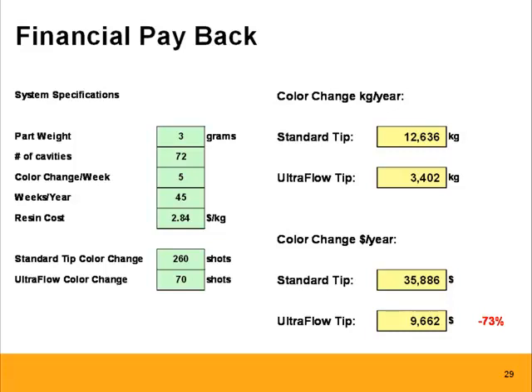Now in regards to dollars, pretty significant savings. $36,000 versus $10,000. So we're talking about a savings from a more effective color change versus a not so effective color change of 73%. That's pretty significant. This was, by the way, just for one tool. So if you run multiples of those, or if you change the numbers from 5 color changes to 10 color changes per week, you can imagine what the impact is.